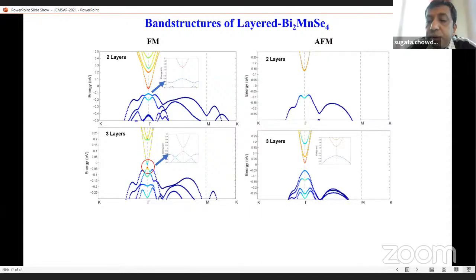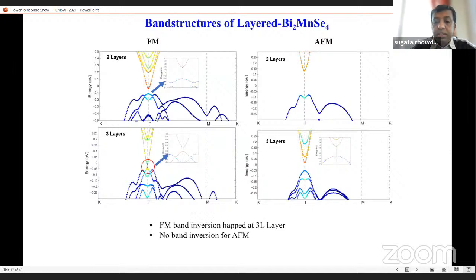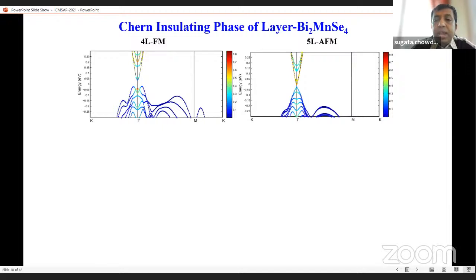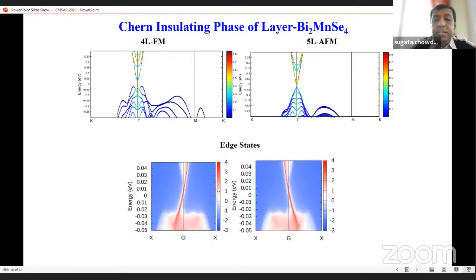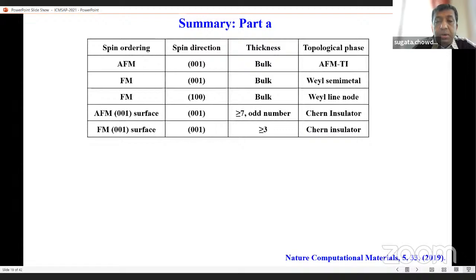Then for the antiferromagnetic system, we notice that in the trilayer there is no band inversion. So three layers of ferromagnetic have a band inversion, but there is no band inversion for the antiferromagnetic system. Then for four layers, in the ferromagnetic case beyond three layers, there is topological property present, but in the antiferromagnetic case it needs to be thicker than that. And we found there is an edge state, and this is how the edge state shows in different directions in our cases.